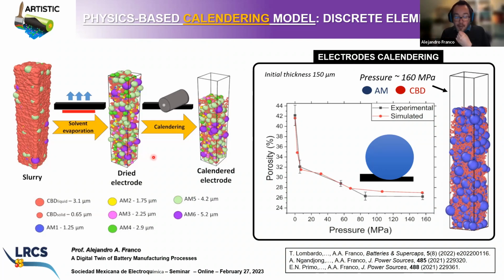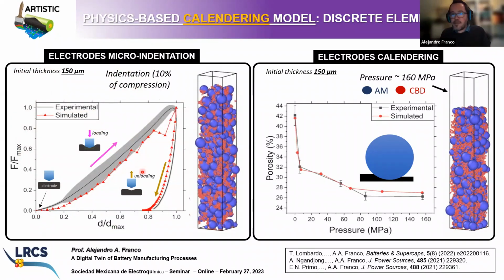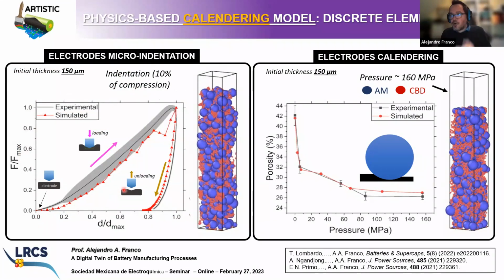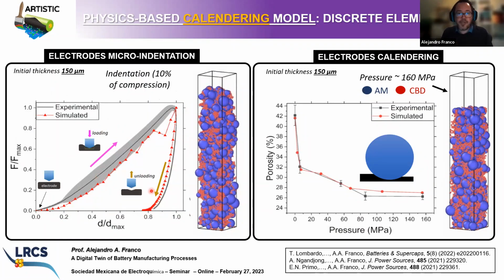Another point which is very important to highlight is that the parameters in these models are determined by fitting the micro-indentation characterizations that we have performed in collaboration with the University of Lille, which is near the city of Amiens, the city where my lab is located. In this micro-indentation experiment, you basically use an indenter to press into an electrode, and then you measure the resistive force of the electrode against this indenter.